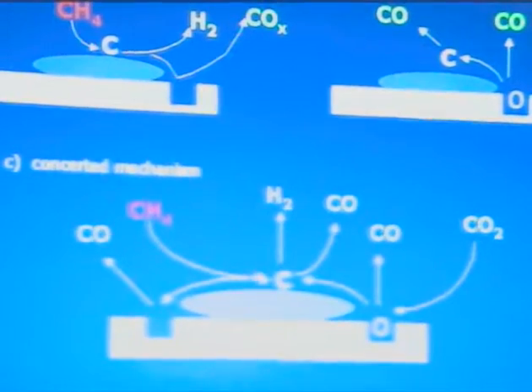What we found is that it was the balance between the rates of that decomposition and the dissociation which determined the long-term activity and stability of the material. So materials that were able to do the decomposition step well as well as the dissociation, and be reducible, were the ones that showed the best activity.